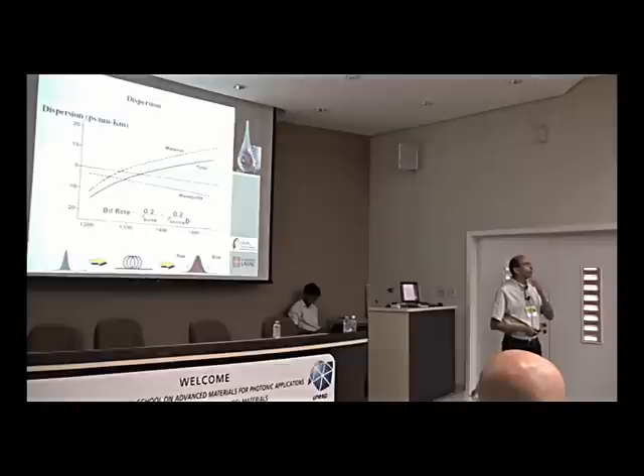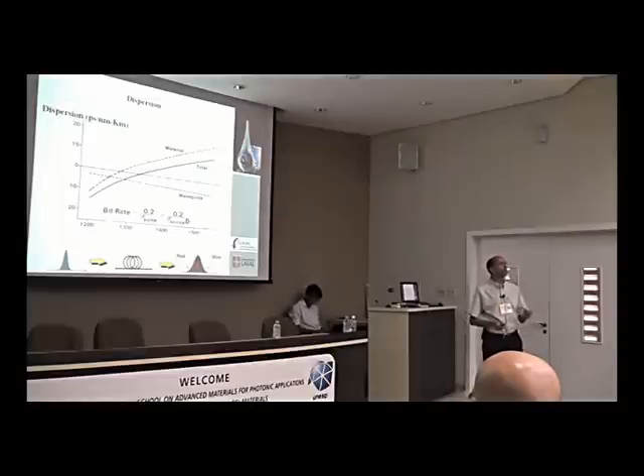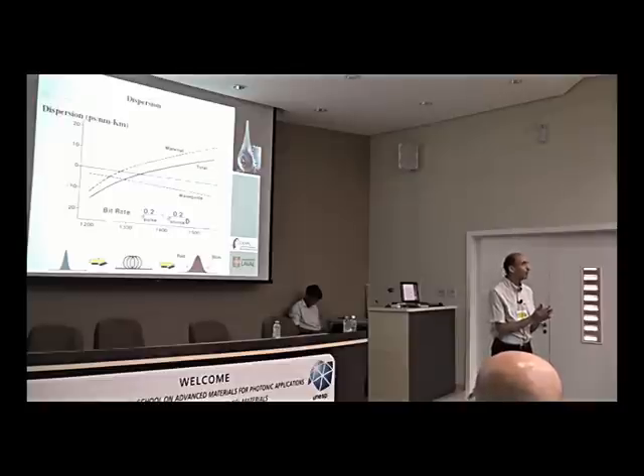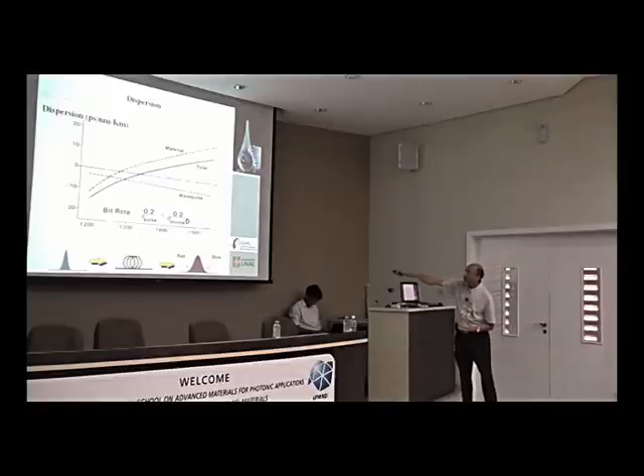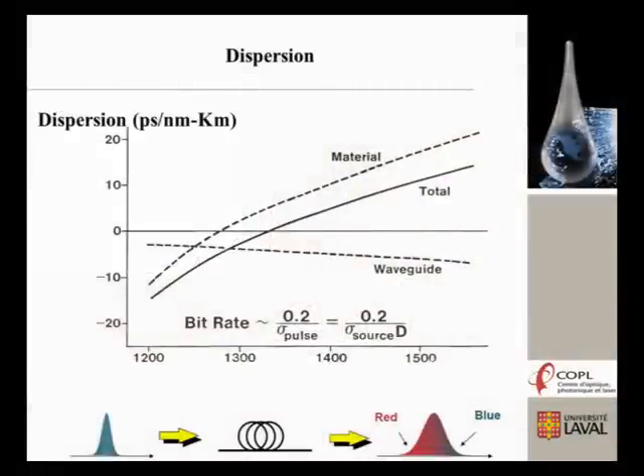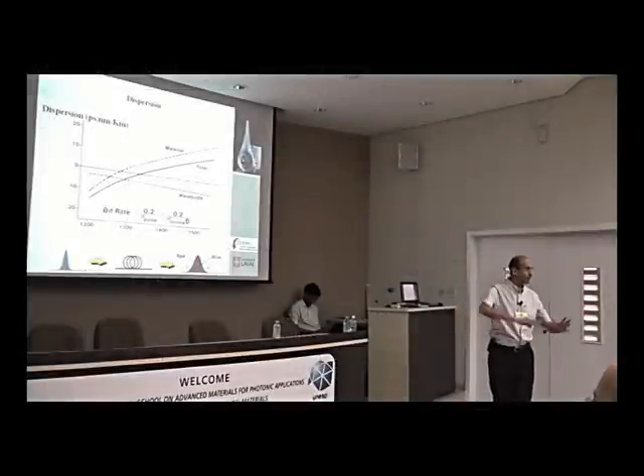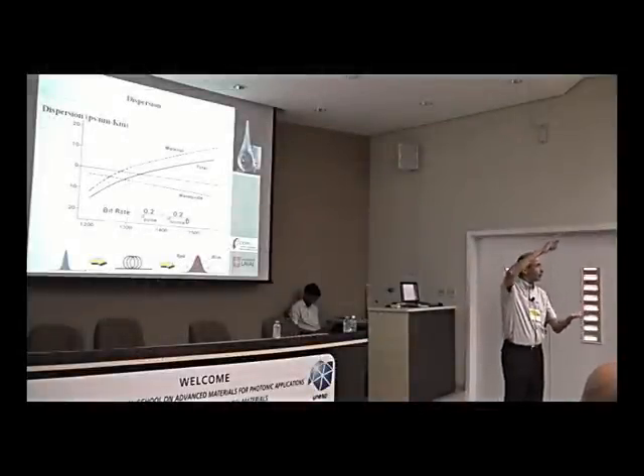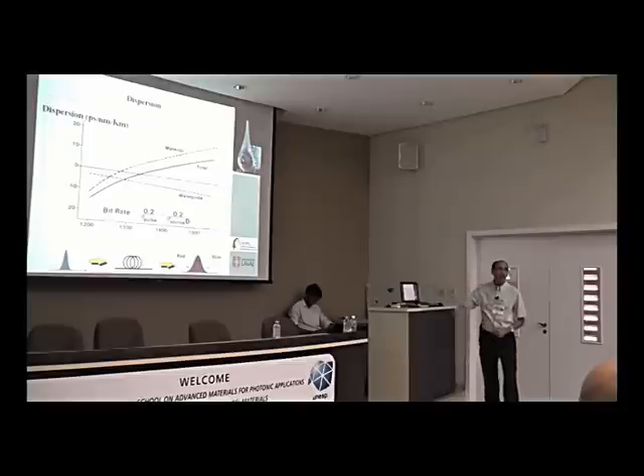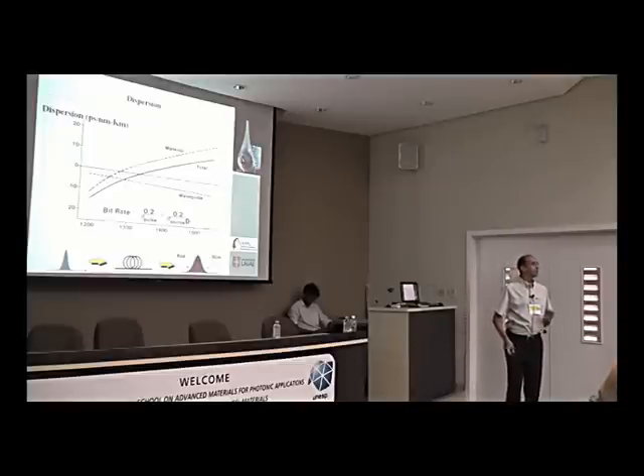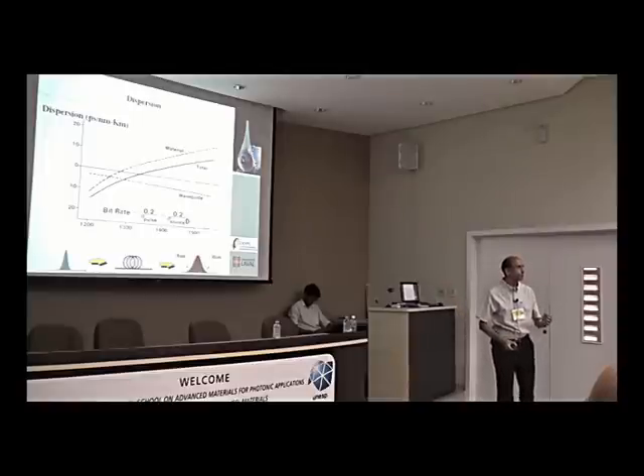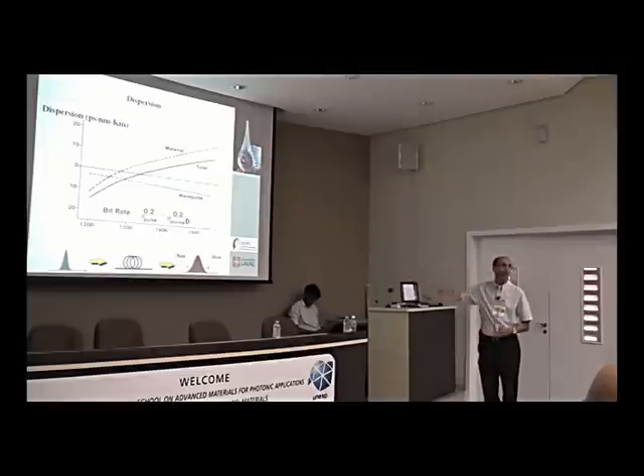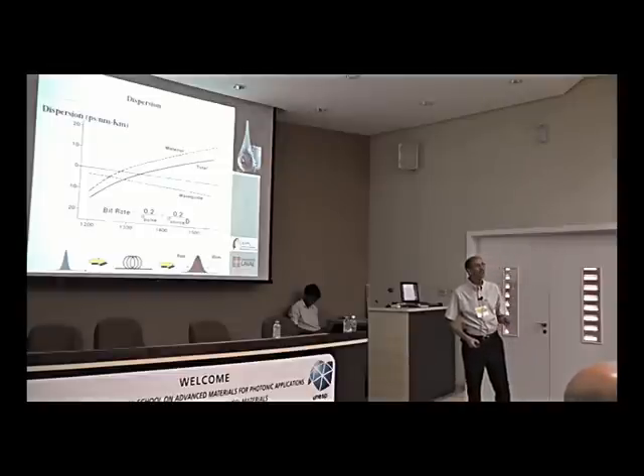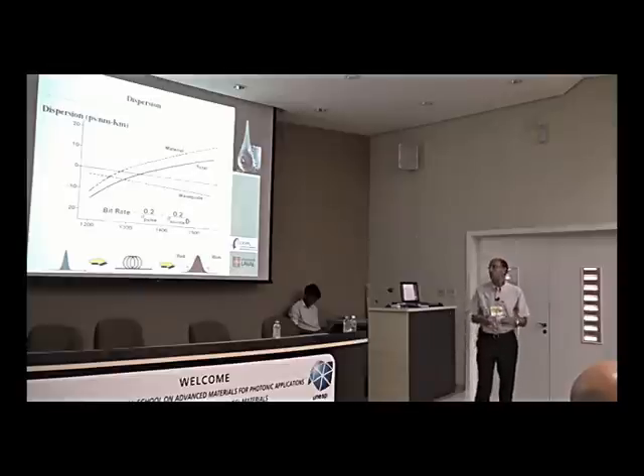Okay, besides that, we also need to measure the dispersion. The dispersion curve is so important because it will affect the signal of our light. There are two parameters: the dispersion of the materials, coming from the refractive index of the materials, and the dispersion due to the waveguide. And if you attend the course of Professor Rebolledo one day, he did all the theory of that physical thing, explaining each component, and the total of that will give us the total dispersion or the zero dispersion at a specific wavelength. Why are we looking for the zero dispersion? Because any positive or negative value will affect the signal of your transmission light, and it comes with some noise in the signal that we have.